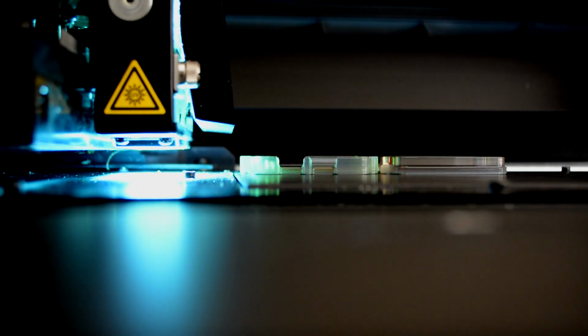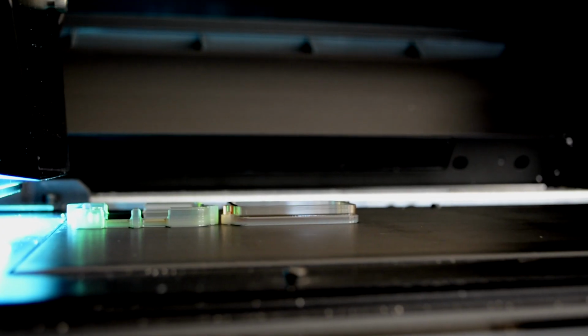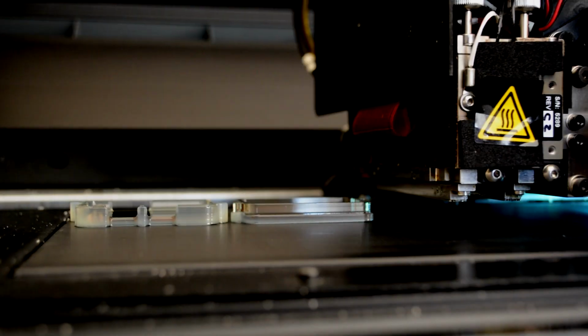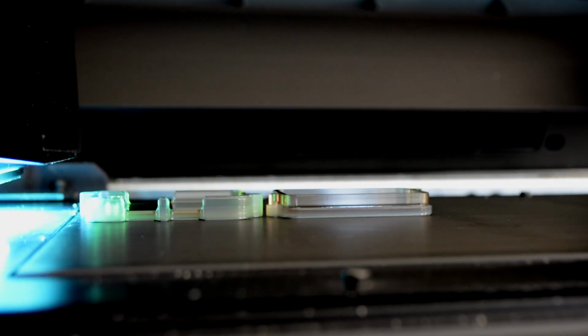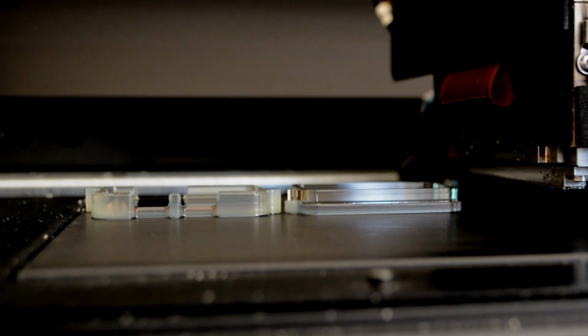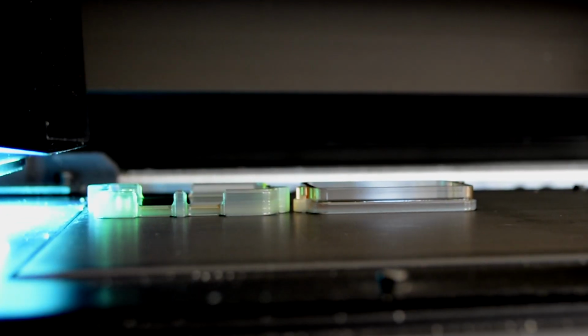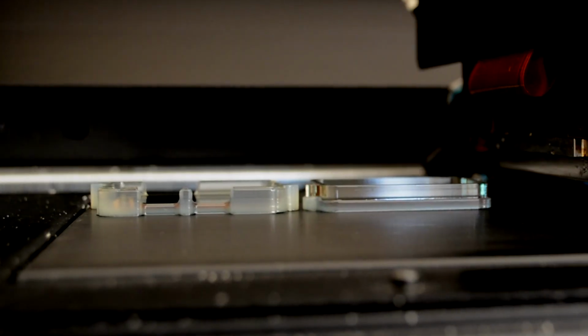The state-of-the-art printing process uses printheads similar to those used in inkjet printers to deposit millions of droplets of photopolymer resin onto the build tray in 16 micron layers, which is a fraction of the width of a human hair. Photopolymer resin and a soluble gel-like support material are deposited simultaneously, layer by layer, and after each pass, an ultraviolet light cures the liquid resin. After each layer, the build tray drops by 16 microns, and another layer is printed on top.